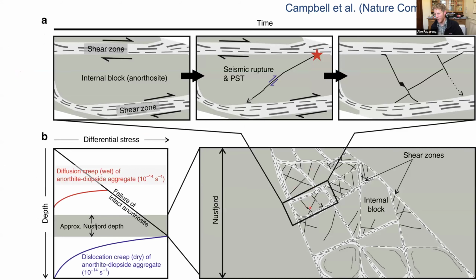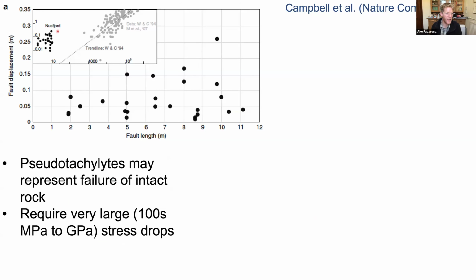So in this case, the localization is not related to a decrease in strength, but rather to an increase in stress. And the stress drops are very different from what we get in wet rocks, which is not surprising. Here we're dealing rather with something that's maybe failure of intact rock, very large stress drops. If we look at displacement against length for these pseudotachylites, we're looking at centimeters to tens of centimeters displacement, fault lengths of meters. If we put that on the same plot as earthquakes, they are much smaller, but they would fit a stress drop line of more like hundreds of megapascals to a gigapascal.